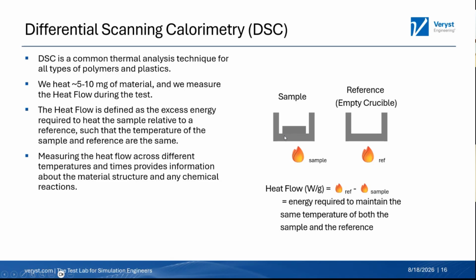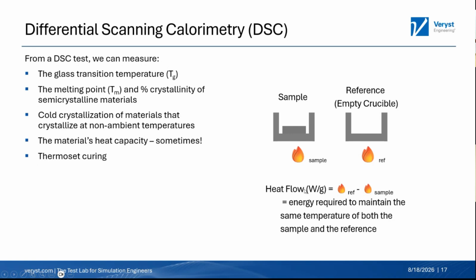You can take an extract from a product that comes off of a tool, comes out of the field, without having to worry about creating a nice mechanical test sample like you do with the DMA. But what we're actually measuring is the amount of energy required to maintain that heating rate in the sample relative to the reference. So if you take basically the difference between the heat flow for the sample and the reference, it is the actual output of the DSC. And so using that curve, that heat flow versus temperature curve, which is the specific result of the DSC, we can actually measure Tg, we can measure the melting point and the percent crystallinity.